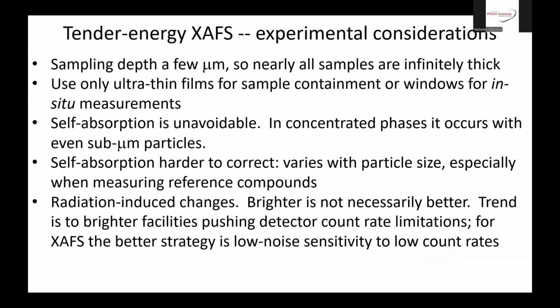There are also experimental considerations. Again, the sampling depth is a consideration, so knowing where that is. But that also means that you can't have very much in front of your sample, such as using a really thin film to contain a sample if it's a powdered sample, or cover a sample to protect it. So you only use ultra-thin films for windowing material or sample covering material. Otherwise, it will just block the beam.